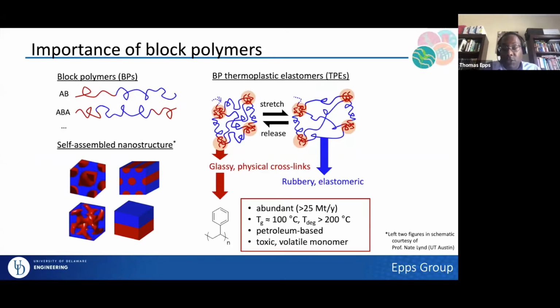In this particular case, I'm just going to mention one particular example, which is thermoplastic elastomers, where instead of just AB, we want ABA block copolymers. The reason for that, as you can hopefully see here, is that I can start having glassy regions, in this case made of a styrene or polystyrene mimic, that I can stretch and release, and think of something like my rubber band, where I can stretch it, release it, and it goes back to its original shape. And part of that is because I can take advantage of some of the self-assembly that I get from having that block copolymer chain architecture.